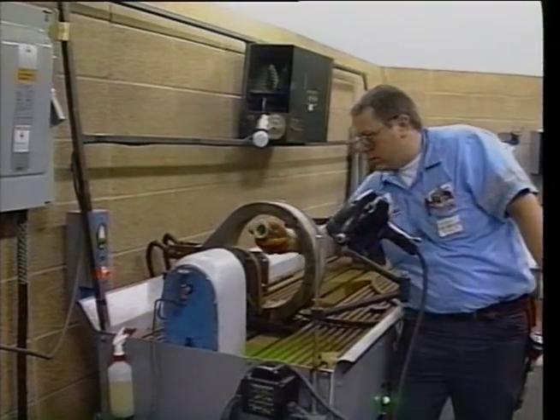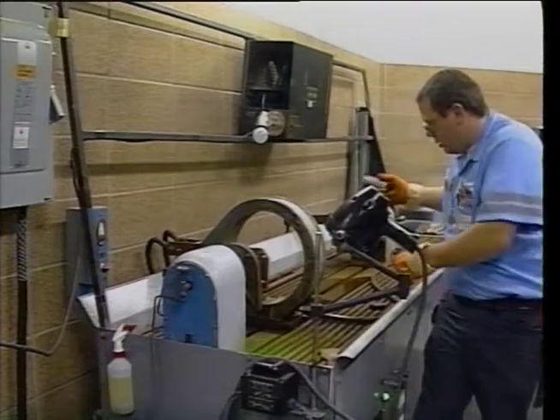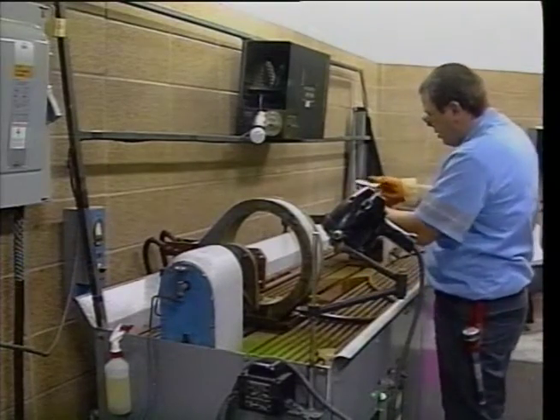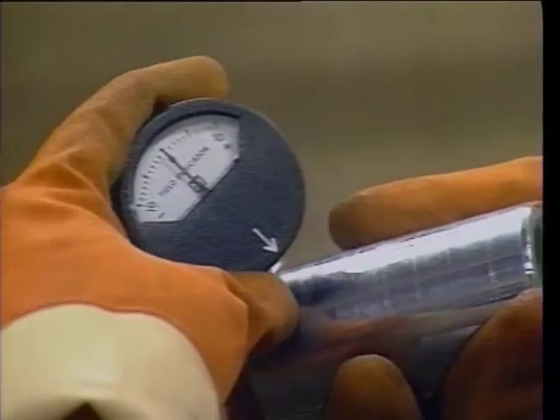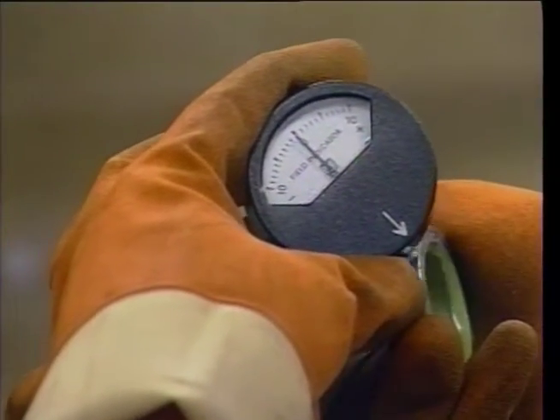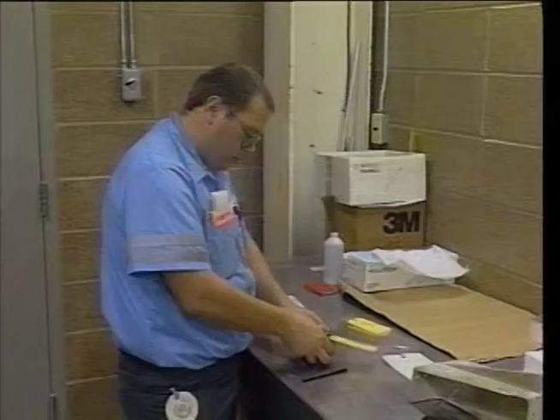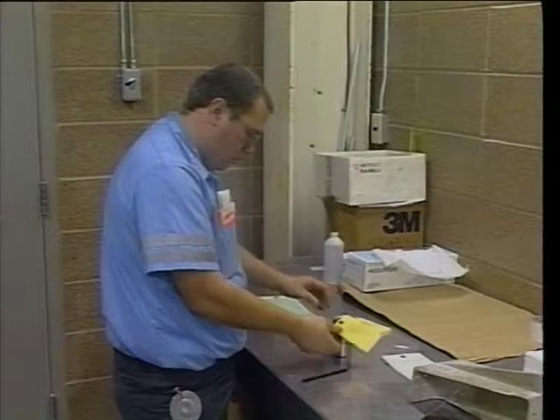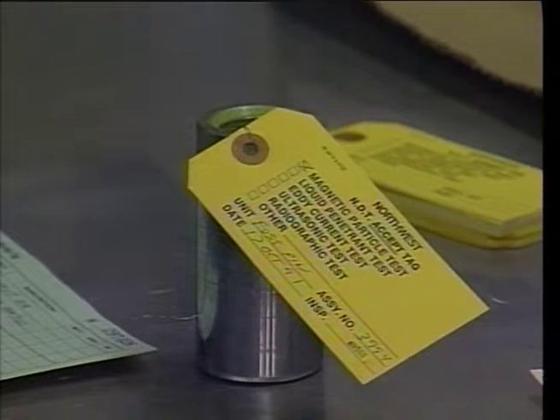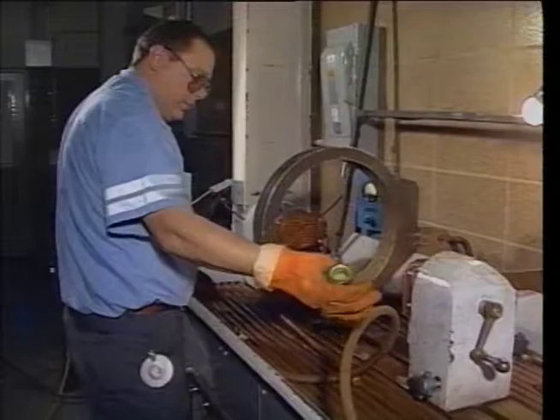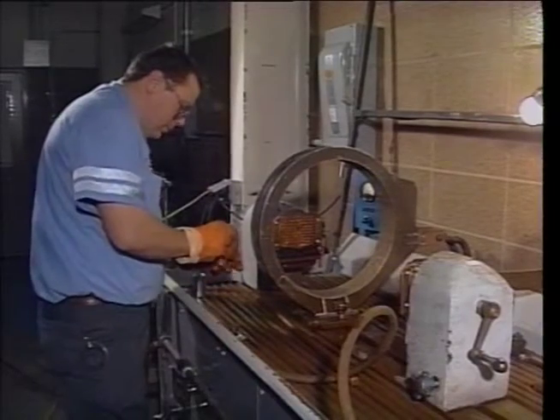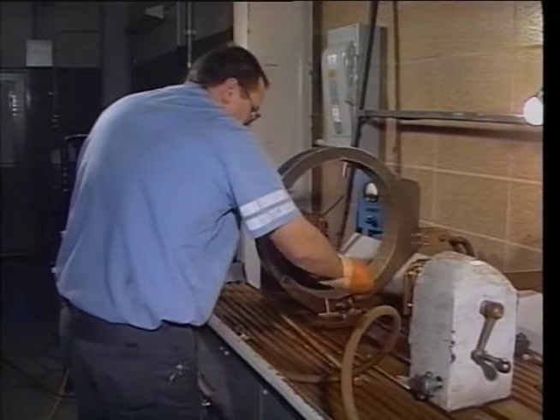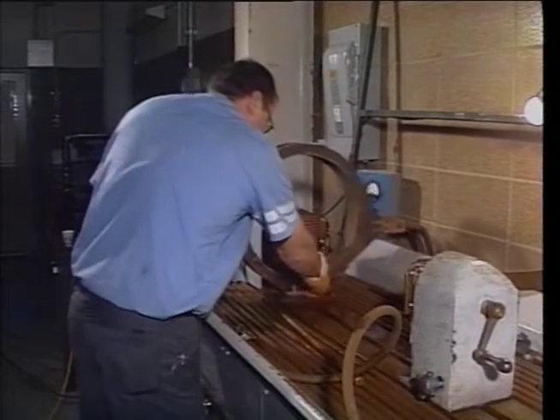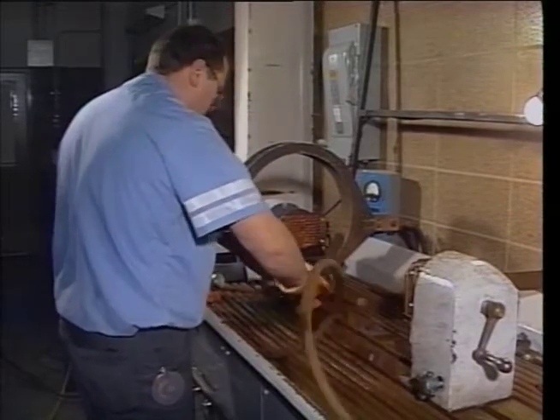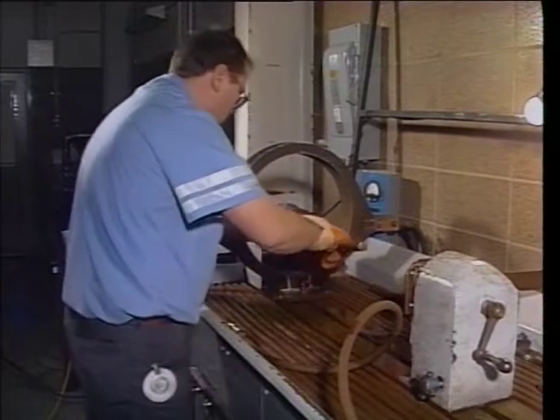Following successful testing, the part is demagnetized to avoid the potential of residual flux attracting filings or interfering with navigation gear on the aircraft. No flaws being detected, this part is tagged OK for reinstallation. Although limited to ferromagnetic materials, magnetic particle inspection has proven a highly reliable method of detecting flaws at or near the surface.